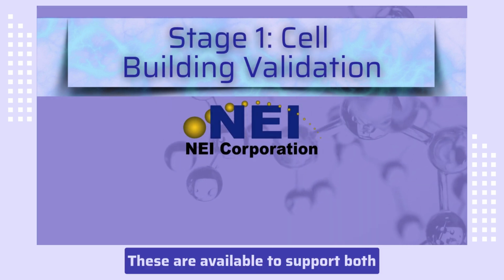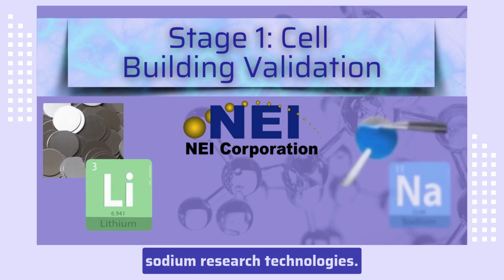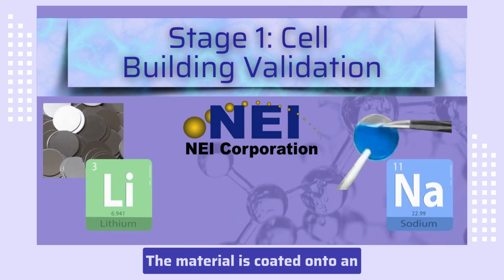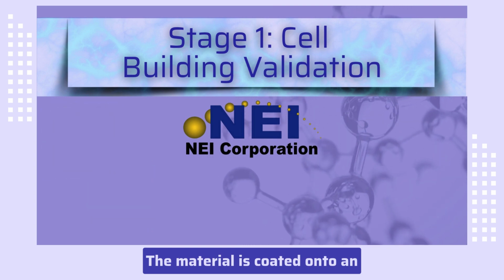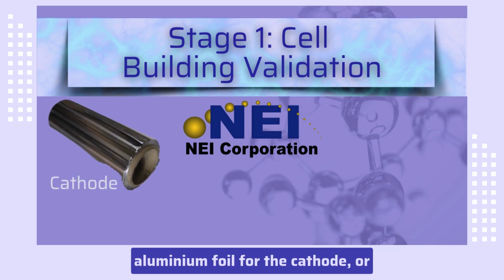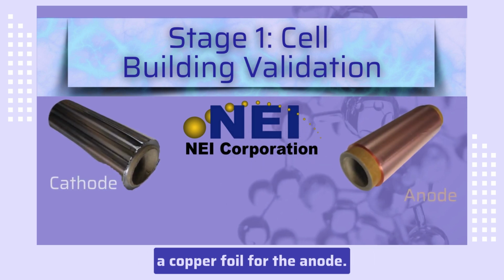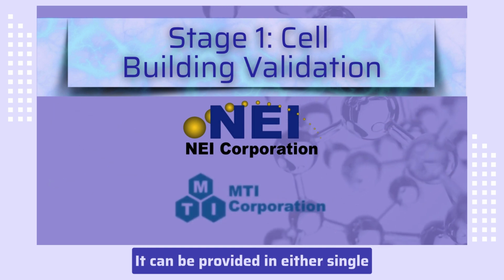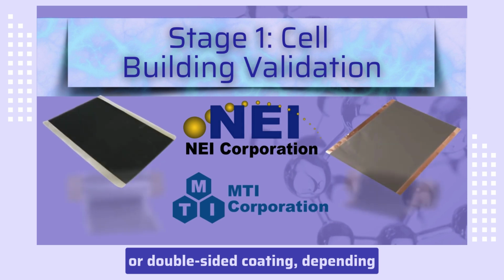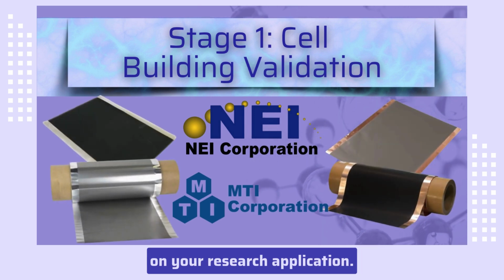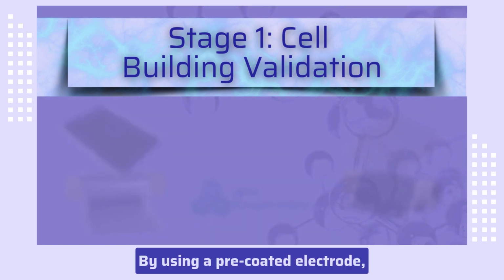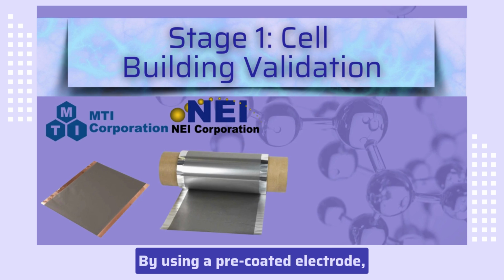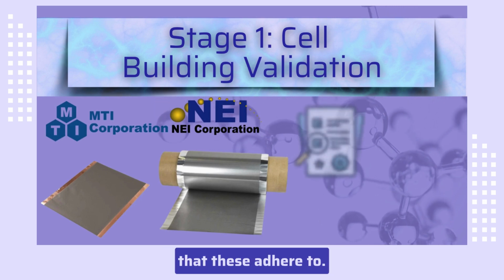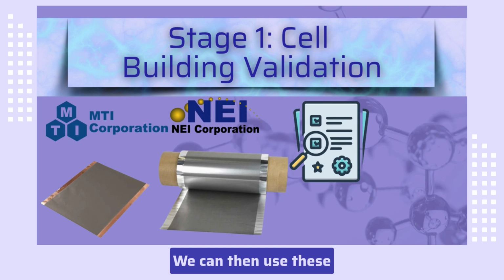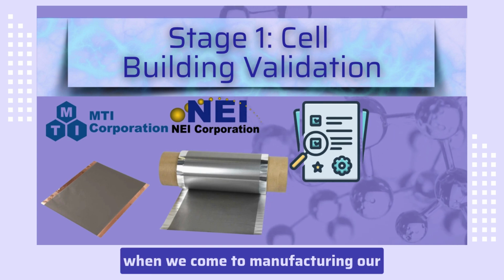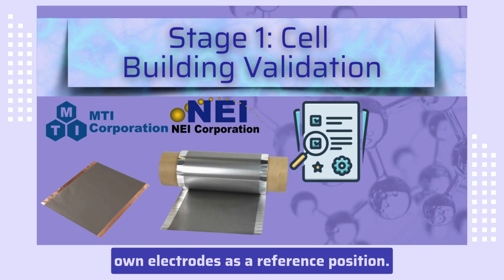These are available to support both lithium and sodium research technologies, and the material is coated onto an aluminium foil for the cathode or a copper foil for the anode, and it can be provided in either single or double-sided coating depending on your research application. By using a pre-coated electrode, we have predefined specifications that these adhere to. We can then use these when we come to manufacturing our own electrodes as a reference position.